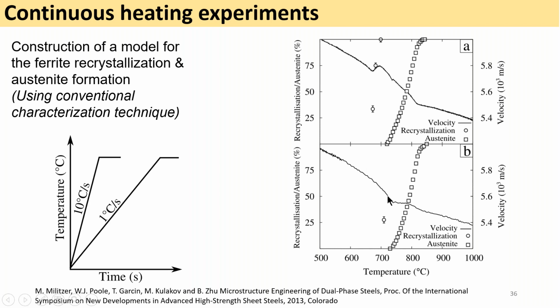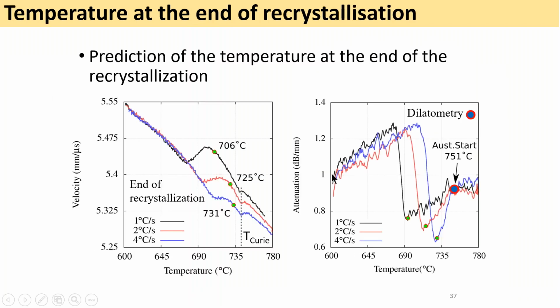We see no sharp increase related to recrystallization up to the austenite formation. When we see here, at a lower rate of heating, this sharp increase due to recrystallization. So we could use this machine to determine that the recrystallization has occurred before the formation of austenite. This is here this illustration at different heating rates. You see at low heating rate, recrystallization occurs fully, while at high heating rate, the recrystallization occurs much later and overlaps with the austenite formation.